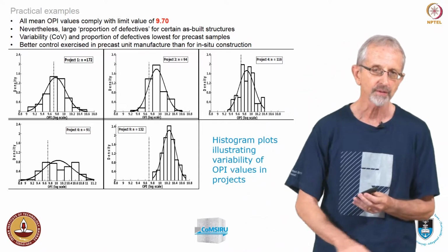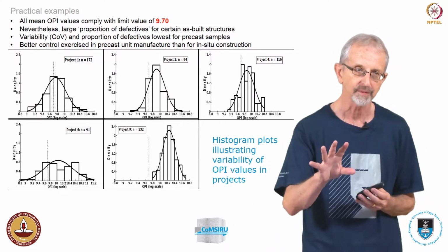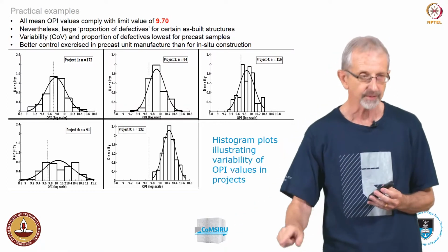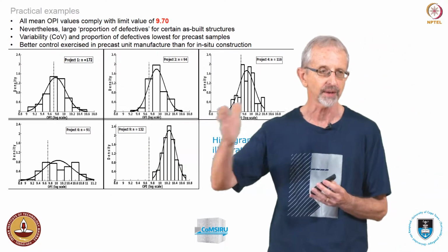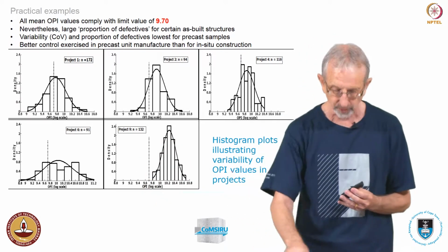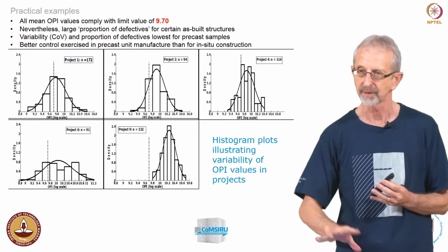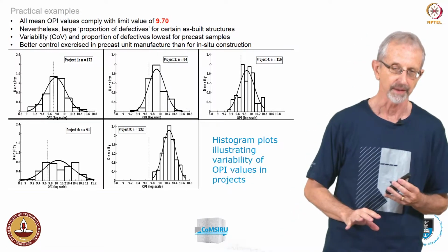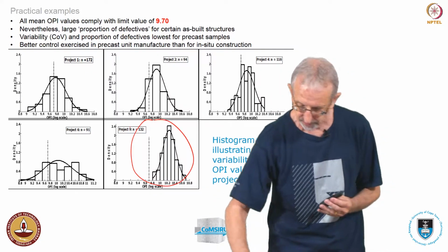Basically the concrete going into these 5 sub-projects was all the same concrete, coming from more or less the same plant. However, the difference is the contractors, the actual execution that was given out in 5 separate contracts to 5 separate contractors. And this is what the contractors did with the same input material. This is what they did on site to the concrete, if you like. And so, of course, the best one was down here.